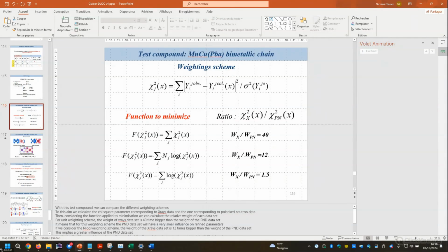In fact we developed a different weighting scheme, and I can show you what they are. This is what we did for another compound, which is a manganese copper bimetallic chain. We developed three different weighting schemes. The one which is just a summation of the chi-square, another one which is a summation of the log, and another one which has been proposed by Michel, which is the summation of the n log of the chi-square. It's a way to play with the relative weight of each dataset.